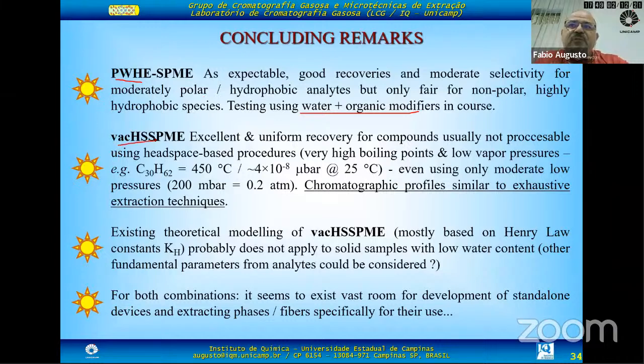With vacuum headspace solid phase microextraction, we have very good recovery for all compounds, especially for compounds with very high boiling points and low vapor pressures, such as C30 hydrocarbons, where we have 4 times 10 to the minus 8 microbars as vapor pressure, and using only moderate vacuum, 200 millibars, 0.2 atmospheres. This is similar to the exhaustive procedure where you need to use 10, 12, 15 days of operation.